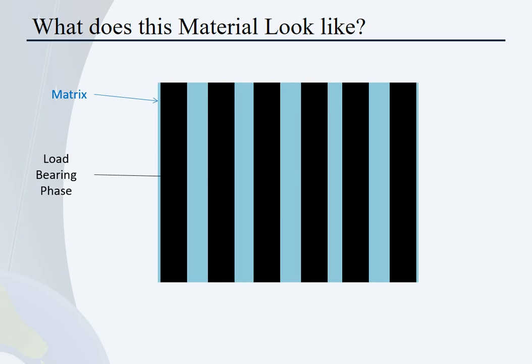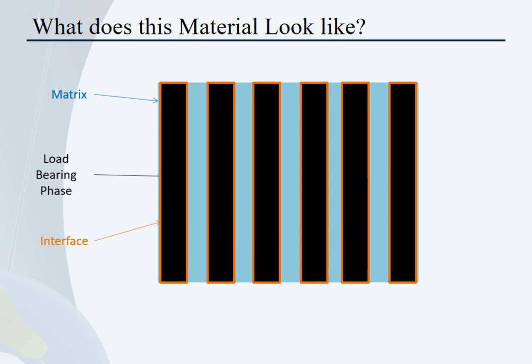Now we don't want a lot of this, just a few percent by mass, because it doesn't really contribute to the load bearing itself. It's fairly weak. What it does, though, is hold all of our tubes together so that they work as one instead of as individual fibers. So that matrix holds everything together and needs to do that under some fairly extreme conditions, which means we need to make sure that the nanotubes don't just pull free from that matrix. And that's where interface design comes in.